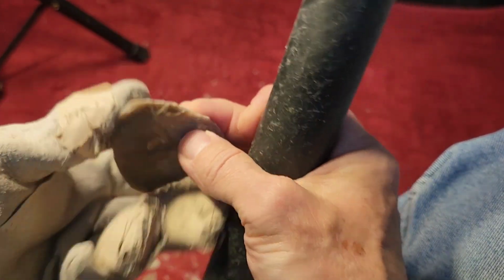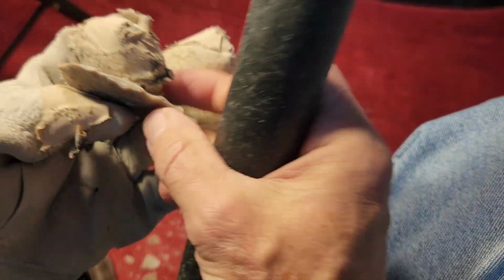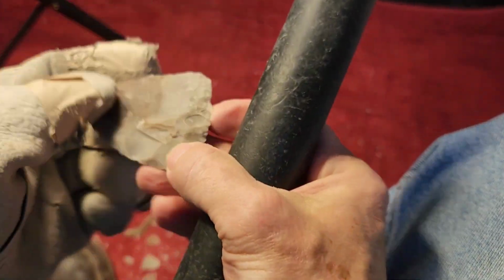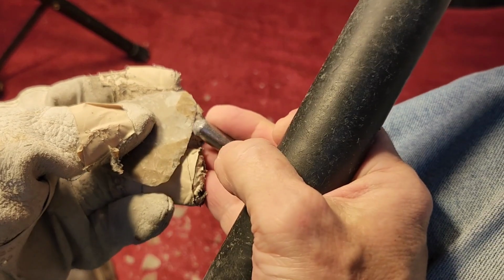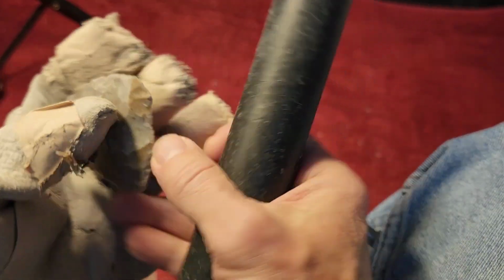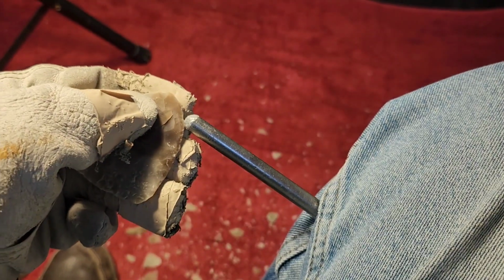It's finicky sometimes. I mean, it's difficult to give you an exact temperature because some of these pieces will respond at lower temperatures than others. So you start the heat treatment at 300, maybe 325 for 4 hours, wait till it cools down, take it out, chip it. If it doesn't work, go to 350 for a couple hours, let it cool down, take it out, chip it. Just keep doing that over and over again until you get to the consistency you want, and the stone is not hurt by subsequent heatings.